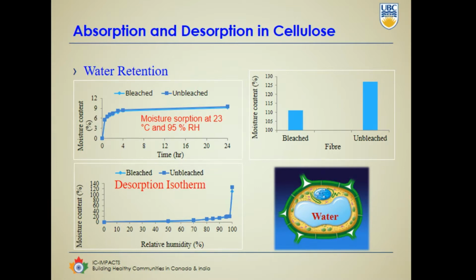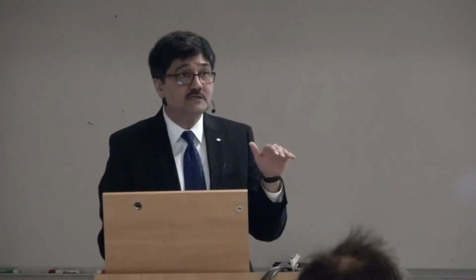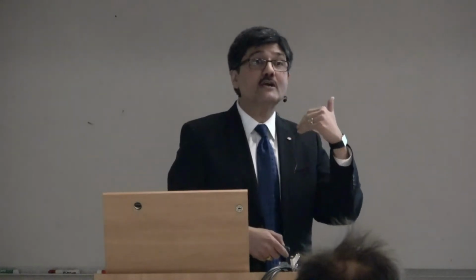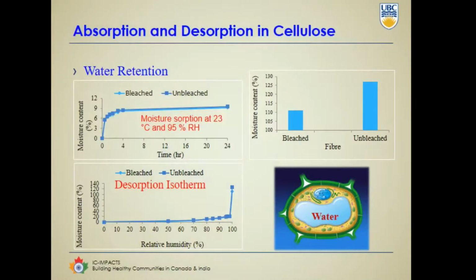But what is also critical is that the moment you lower the relative humidity, that water is actually desorbed very quickly. What that means is you lose that water very quickly the moment the relative humidity drops. And I like that, because I want that water to be released very quickly back to the concrete when there is desiccation, and I need that water back into the system as quickly as the relative humidity drops in the body of concrete. So cellulose is a wonderful material for internal curing of this particular nature.